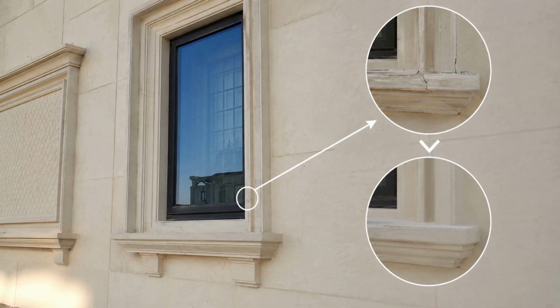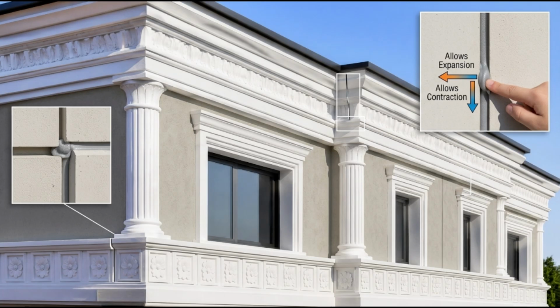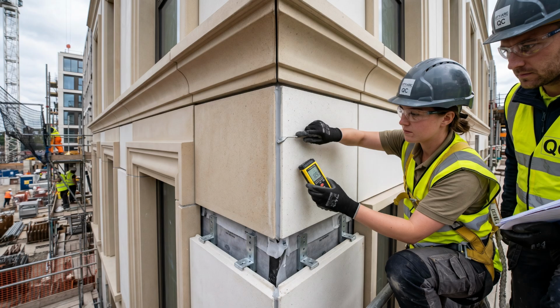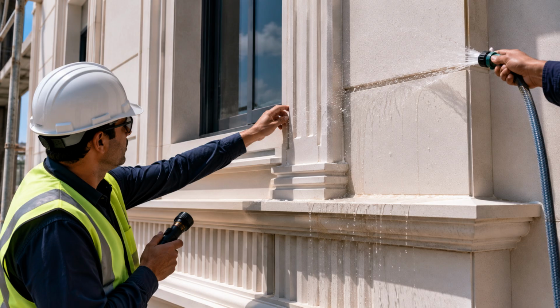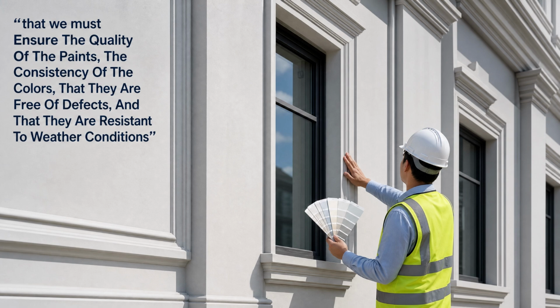Reviewing repairing of any breaks, cracks, or fissures in the mold body. Ensuring that joints are treated correctly in a flexible way that allows expansion and contraction due to temperature changes. Ensuring that the joints are tightly sealed against water and that there are no leakage points or insulation problems, with the possibility of conducting a water test when needed. Ensure the quality of the paints, the consistency of the colors, that they are free of defects, and that they are resistant to weather conditions.